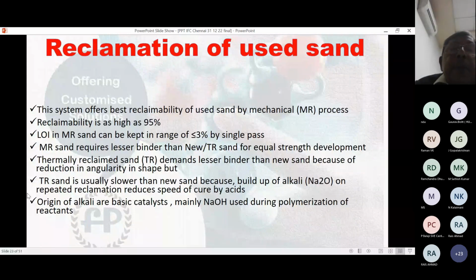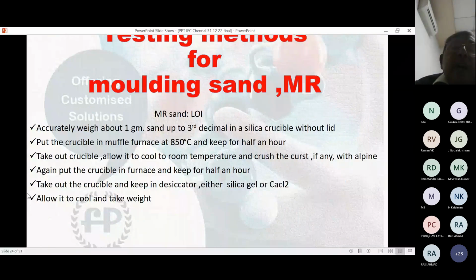Reclamation. This system offers the best reclaimability of used sand by mechanical process. Reclaimability is as high as 95%. LOI in mechanical sand can be kept well below 3% by single attrition. Mechanical sand requires less binder than new sand for equal strength development. Thermally reclaimed sand demands lesser binder than new sand. Thermal sand is usually slower than new sand because of build-up of alkali on repeated reclamation. Origin of alkali in the reclaimed sand is that it comes from sodium hydroxide used in the manufacturing of the phenol formaldehyde resin.